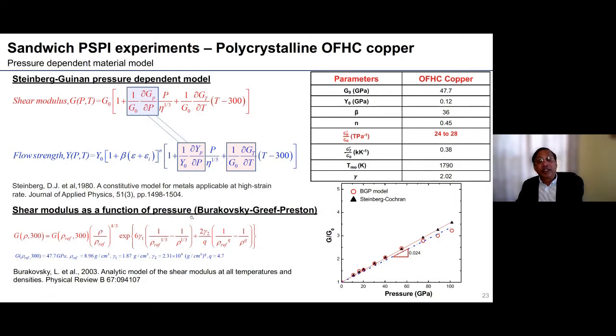And the shear modulus as a function of pressure has also been explored by this very nice model, the Burakovsky-Greeff-Preston model, which gives you a very nice expression for the variation of the shear modulus. So if you look at the Steinberg-Guinan model, or the Steinberg-Cochran-Guinan model, that's plotted in the black triangles, this is what is available in the literature. We have also looked at the Burakovsky-Greeff-Preston model. They agree fairly well. So the slope is about 0.024 as a function of pressure.